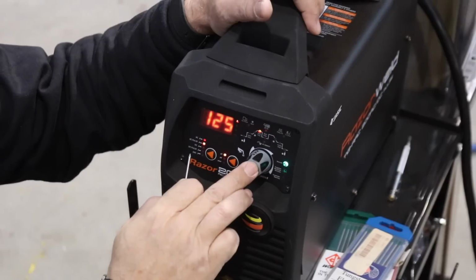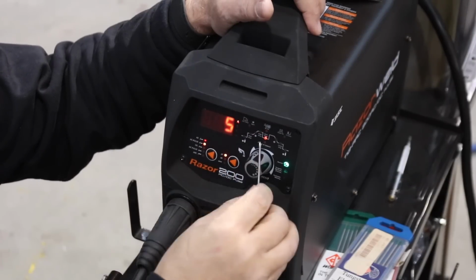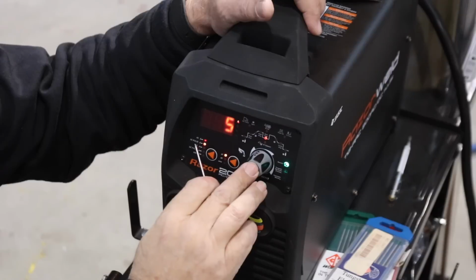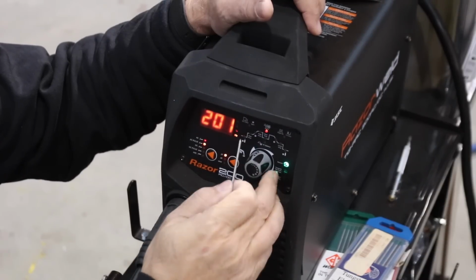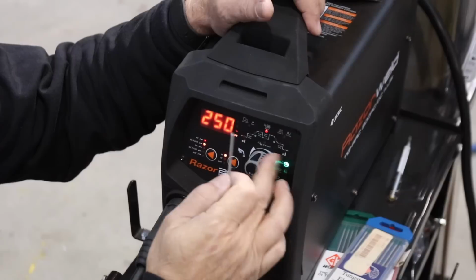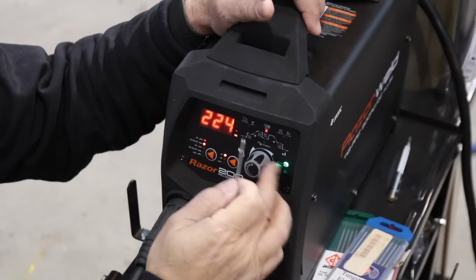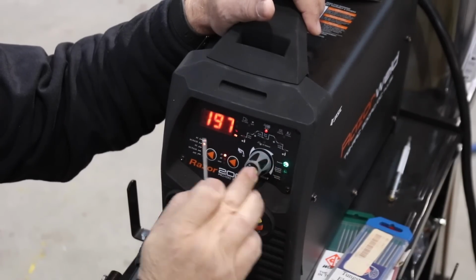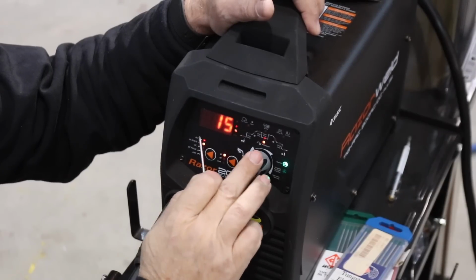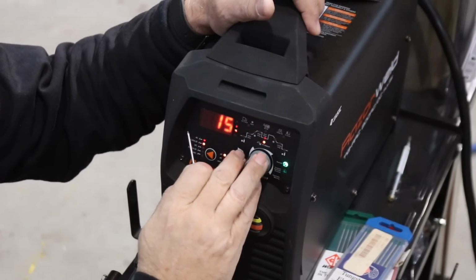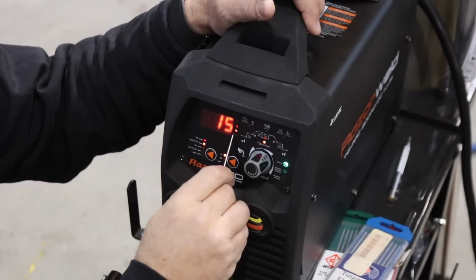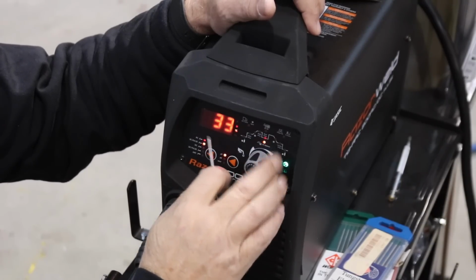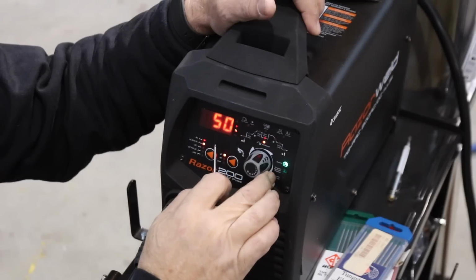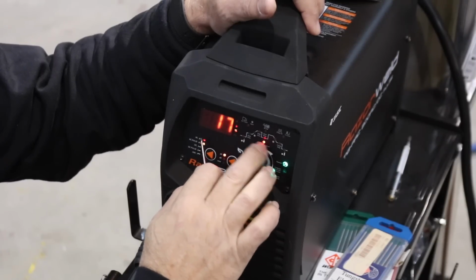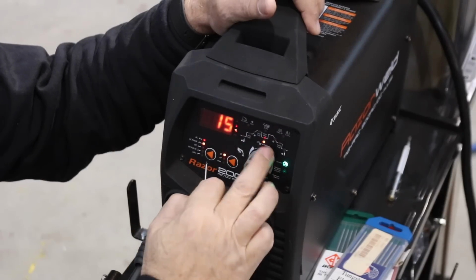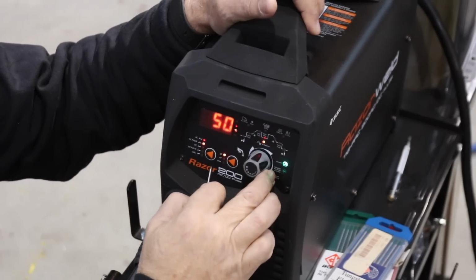Now down here, AC pulse, and that takes me to the base amperage, the background for my pulse. Then this is AC frequency, which goes up to probably 250. AC frequency is adjustable, and then AC balance, which looks to be a percentage of cleaning. It goes from 15 to 50, so it's backwards from a Miller Dynasty. The higher setting is going to mean more cleaning.